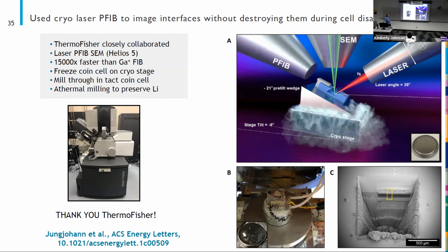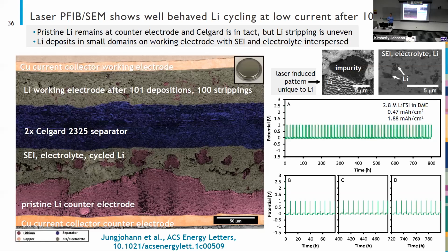So they were susceptible to that. At this time, it was a research tool and they weren't selling it yet. And so they let us come there and do a lot of experiments, and they did a lot for us too eventually. And we were able to get a lot of images with this method. So we put the coin cell on the cryo stage, we mill through it, and then we polish those images.